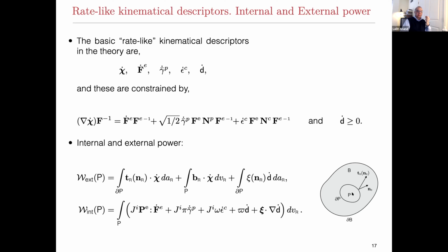And the internal power within the part of the body is an elastic power. There's a stress PE, which is conjugate to Fe dot. There's a stress pi, which is conjugate to gamma bar dot P. There's a scalar microstress omega, which is conjugate to epsilon C dot, and a var pi, which is conjugate to D dot, and a vector microstress C, which is conjugate to the gradient of the damage. So many different things can expend power. All the kinematical variables here can expend power internally. Each kinematical variable has a corresponding stress, either tensorial or scalar or vector stress, which is conjugate to it.